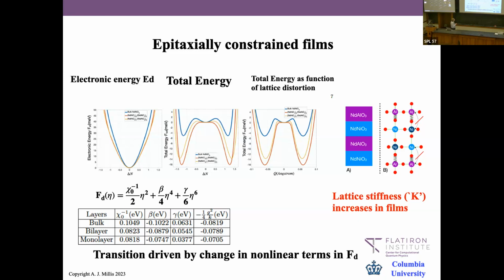You go out in the wings here, and this one, which is a strained film, is much less than that. So what the quantum confinement and strain is doing to the electronic properties is lowering the stiffness in the sense of drastically decreasing the higher order nonlinearities, and not in the sense of changing the linear response — which again somehow goes against everything I was taught in graduate school, where you're supposed to look at the linear response and see what happens.